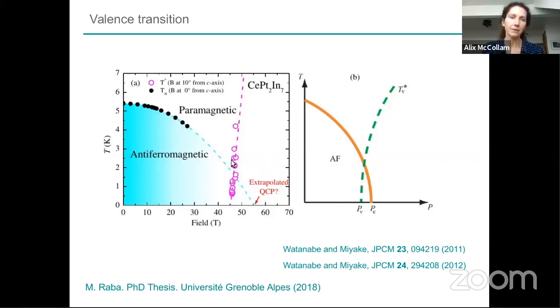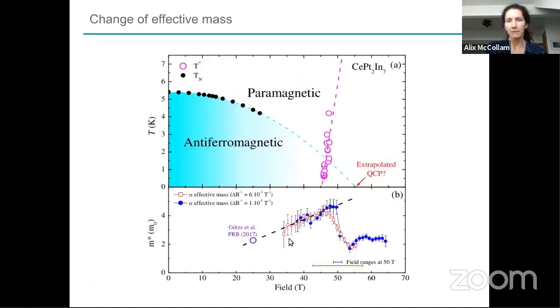So we suspect that this is a valence transition at 45 Tesla, and the Fermi surface does not change across this transition. The effective mass does change a little bit. So this is the effective mass as a function of field, and you can see that there is a change from 3 to 2 or so.